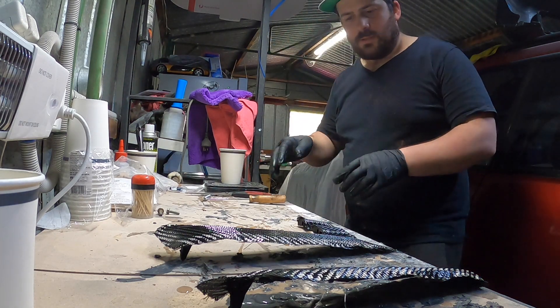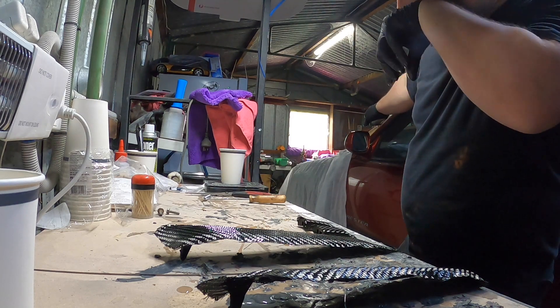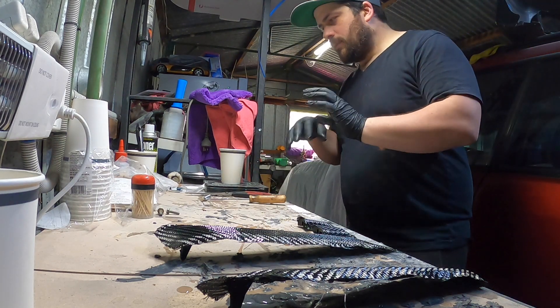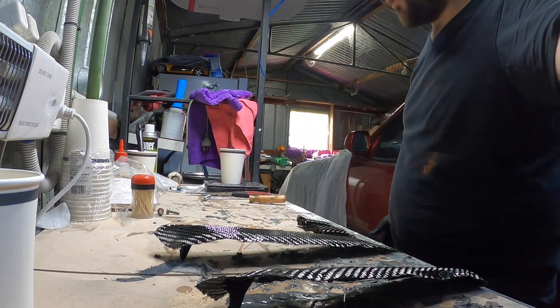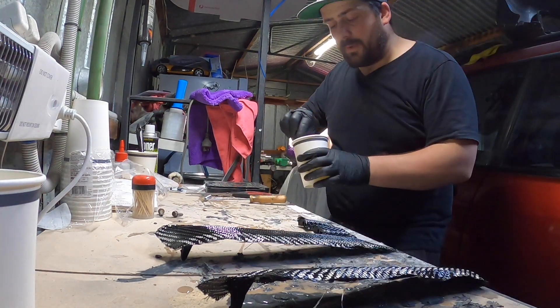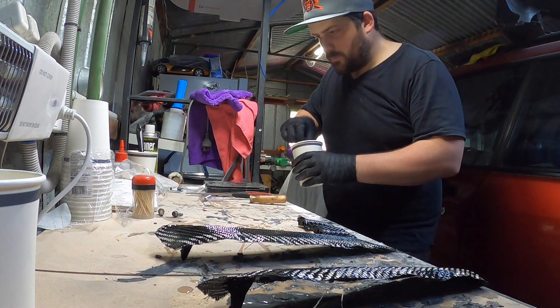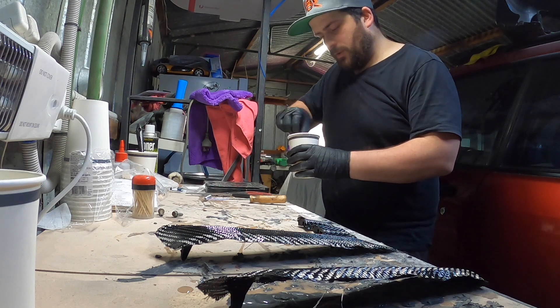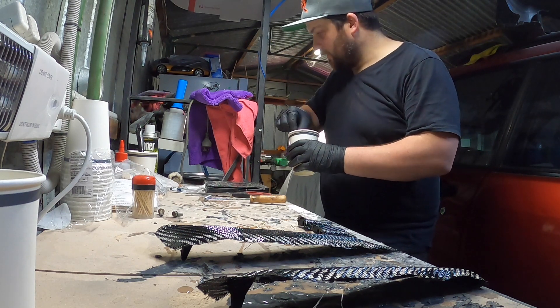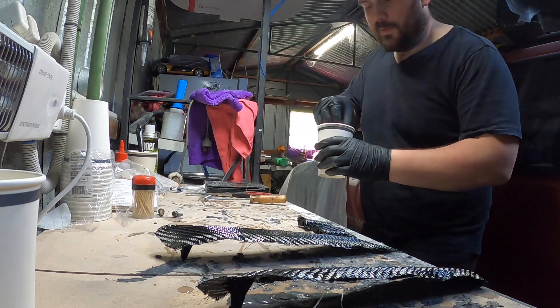We'll get these four done, wrap them up. The door handles are already in the bag - not vacuumed yet but everything else is done. That batch was getting freaking hot. Maybe I just took too long - there was 120 grams in there and just the volume of it created enough heat to make it smoke and nearly catch fire. All hardened with the resin wasted.